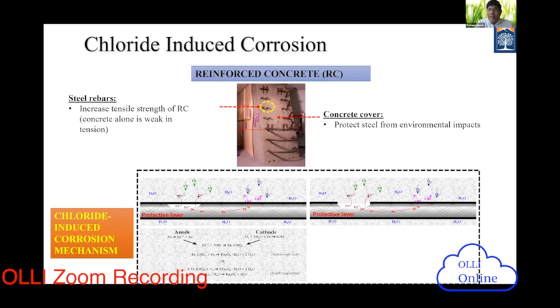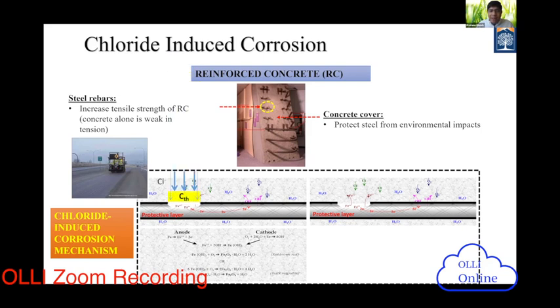But then, in the presence of moisture and oxygen, the chloride salt, as you see from the top, we are putting the salts on the pavement. That salt starts to ingress into the concrete. After a certain amount of time, as you can imagine, the chloride salts coming from the top start to attack the rebar. So the corrosion product starts to increase. Then the problem starts, as you can imagine.